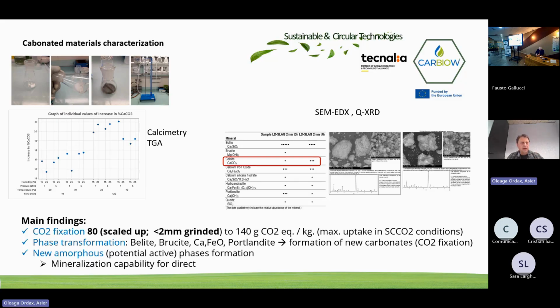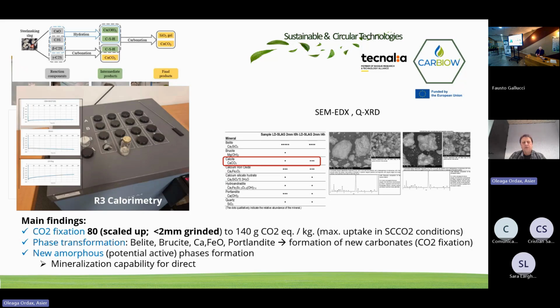We did many other tests, but the principal are calcimetry and TGA to understand how much was the capture, which were the mineral transformations. We see that the calcite increased a lot as expected. And also we analyzed the reactivity, how it changed not only the fixation of the CO2, but also how it transformed to a better product, a better material that can have some sort of activity that can maybe partially replace some clinker.